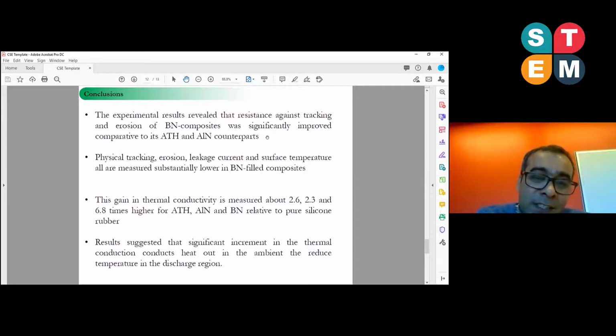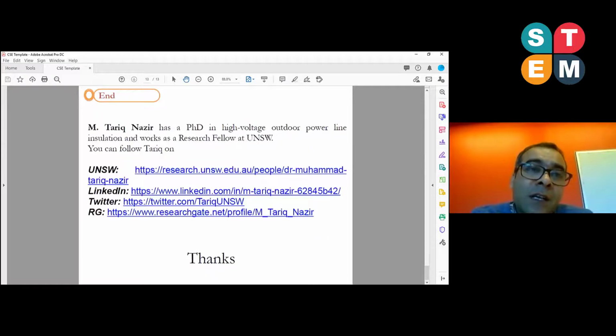So results suggest that the significant increment in the thermal conductivity conducts heat out, like I already explained. Higher thermal conductivity can conduct heat quickly into the ambient, and that can reduce temperature in the discharge region. So that is the major reason how thermal conductivity can improve performance in terms of tracking and erosion.